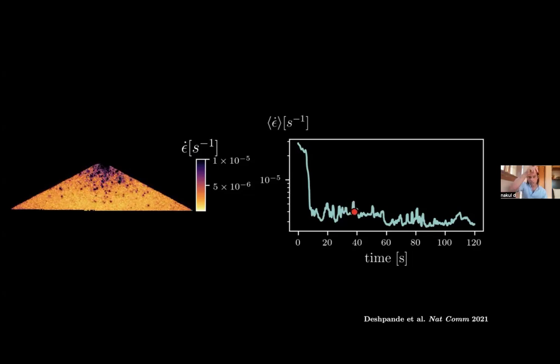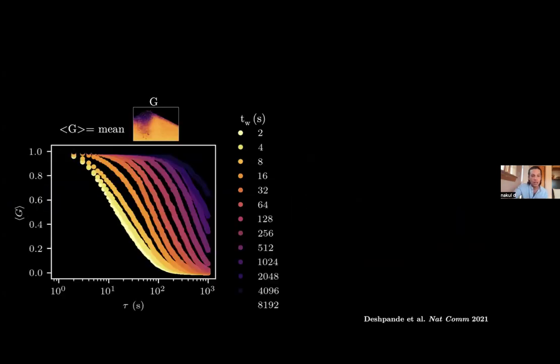So there are fluctuations, and then there's also a decay with the rate and time. So although this system creeps under gravity alone, it doesn't creep at the same rate through time. And we can quantify this slowing down essentially of the creep rate by computing what is a correlation function, okay? So the way that I want you to think about this is that you can compute how statistically a speckle pattern at one time resembles a speckle pattern at another time, okay?